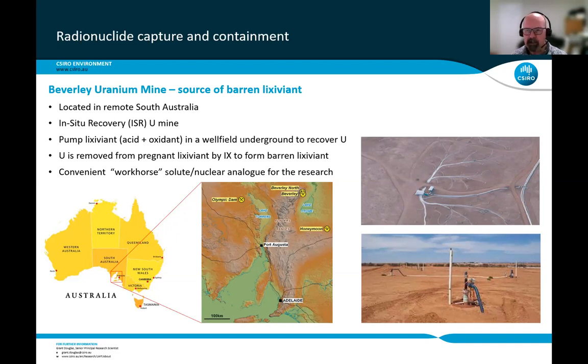And putting that acid and the oxidant in, they're able to recover uranium. But what also happens is when you dissolve up the uranium, you also dissolve up a whole range of the daughter radionuclides and a whole range of other contaminants that are associated with the uranium mineralization. So what's known as the pregnant lixiviant, which is full of uranium, is pumped up to the surface. They then use ion exchange to form a barren lixiviant. Now, this barren lixiviant is then refortified, and it's used over and over again, being pumped into the aquifer to recover more and more uranium.